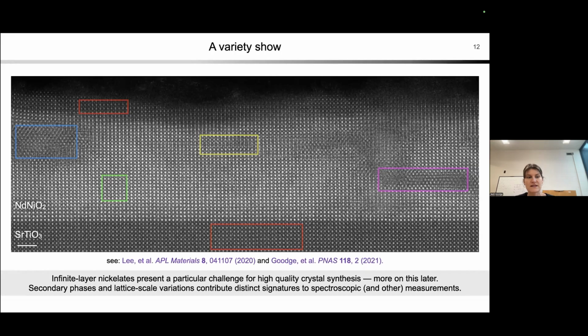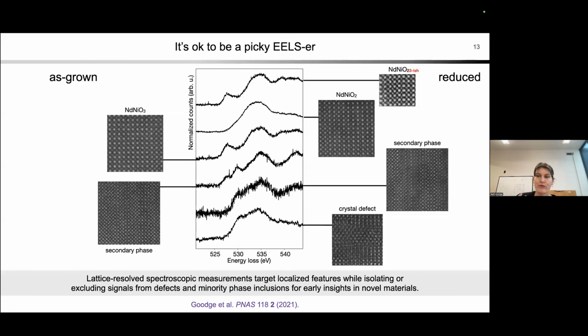But you also see, for instance, in the blue and the yellow and the purple box, these regions that are kind of secondary or defective crystalline phases, right? And so it's kind of messy. There's a lot going on. And that's fine. The thing still superconducts. There's still a lot we can learn from these samples. We're not sitting here waiting for the most perfect crystal to emerge. But it's important to keep in mind as we want to actually learn about the physics of these materials so that we can, again, kind of keep going on this journey to understanding and designing better superconductors.